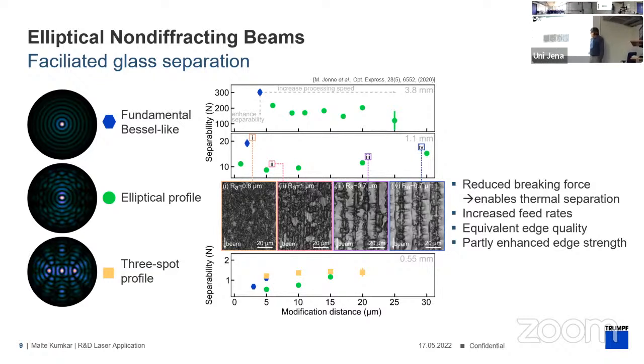And then the appearance is different. The modifications themselves normally are scattering, so this is shiny, but in the cracks, this is reflecting. So the appearance is really different, and for some design people, it's very important. The other thing is that, of course, in case you can increase the distance, the feed rate can be increased. You get equivalent edge quality. The roughness is below 1 micron typically. And very often you can generate partly enhanced edge strengths by this preferential direction of these beam profiles.